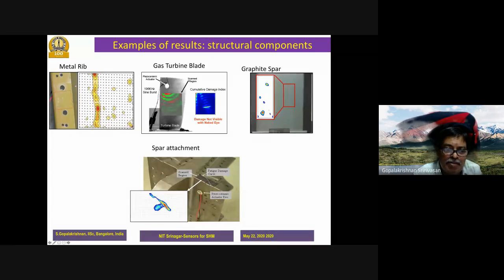We could use this laser vibrometer technique to actually find out exactly where the damage is. This is the manufacturing defect. Every composite is prone to porosity. And if the pores are more than 2% by volume, it is not aerospace grade. We had a Boeing project, and they gave us a sample with different levels of porosity, and we used this technique to find out exactly where the high levels of porosity are. And this is the wing spar attachment, where the damage scenario was the laser was put on the top surface, but the vibration was triggered in the other plane.